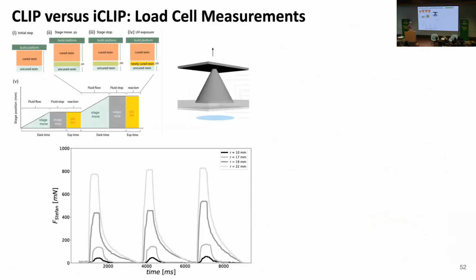And what's interesting is when you have a platform holding a part, it's kind of like having a drop of water between two sheets of glass. It's hard to pull them apart, right? You can slide them, but it's hard to pull them apart. Well, we're pulling two parts away with a liquid between them. It's kind of like that. And so if you had a force, and we put a load cell on the platform, you could pick the platform up, stop, and then watch the liquid flow in. And there's a stress relaxation with that. Pick it up again, liquid flows in, and you can illuminate at different points on this curve to make a pattern. And depending on the cross section, there's more force if it's got a higher cross section than the smaller cross section. That's for traditional CLIP.